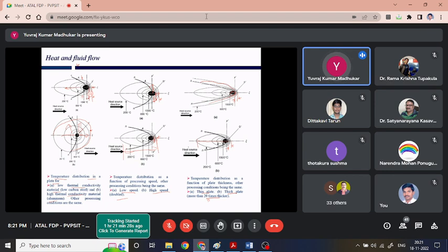Here, with the help of different diagrams, the bottom line of the information I was trying to share is that, with respect to the material, whether it is low thermal conductivity or high thermal conductivity, with respect to the speed, and with respect to the plate thickness, the temperature contour is always going to be less at the front, and it is going to be more behind. Now, if it is behind, then sensing the temperature in this zone is probably going to give us more freedom, or a wider area, where we can make the control system work.